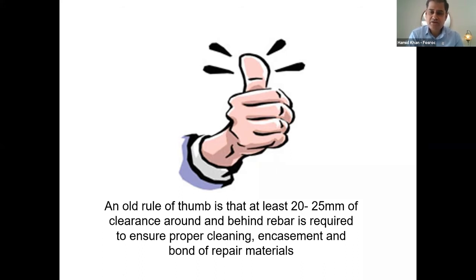So you have repaired an area with corrosion prevention, with a galvanic anode for a patch repair. But for the areas in the same structure or floor, it's very easy to do a condition assessment survey, with chloride dust sampling, chloride profiles, and carbonation testing. And then we can see that, hey guys, it's really important to protect that as well, because it's the same part of a structure. And the client or the asset owner is looking for the design service life to be extended by so many more years. So definitely then, we are not going to break that whole area. We're going to drill holes and apply those corrosion control anodes.